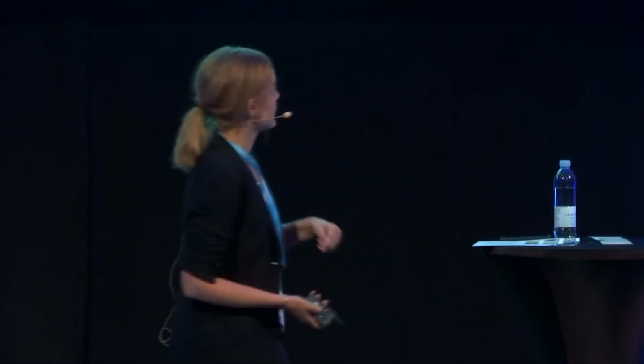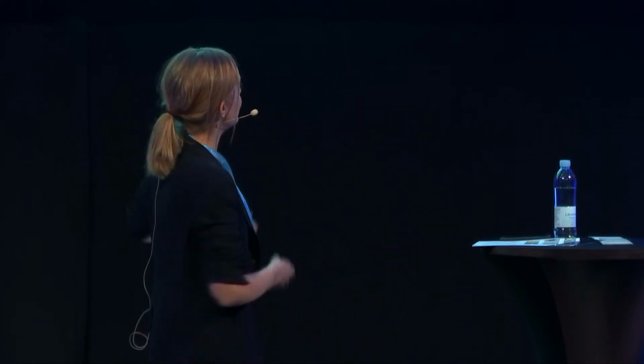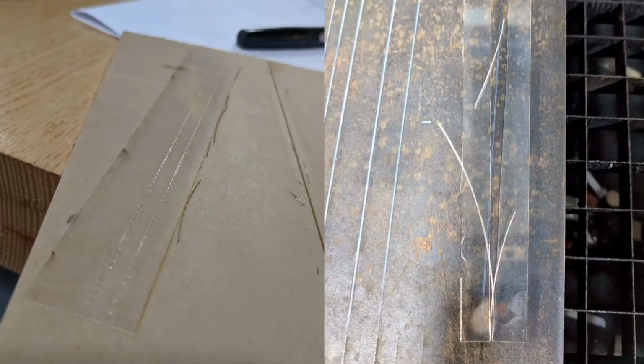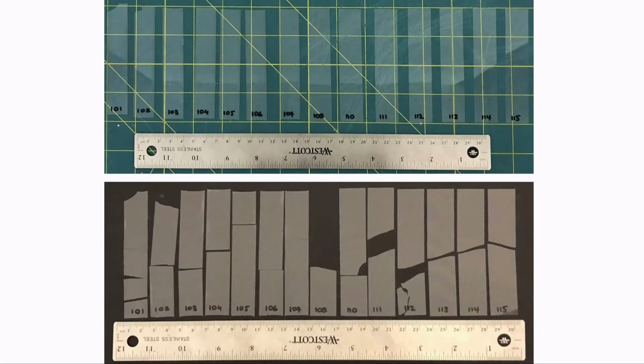Another thing to be noted is the focal point of our laser didn't match the top surface of the glass, probably because of some backing surface thickness, and resulted in cutting those very interesting stripes of glass where you'd have a left side and right side of the laser. So that resulted in this phenomenon which we had to account for in our fabrication process. And then we submitted those samples to bending.